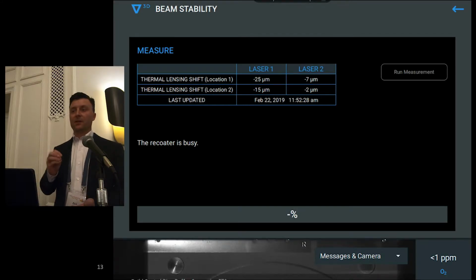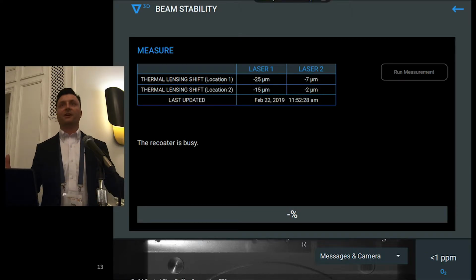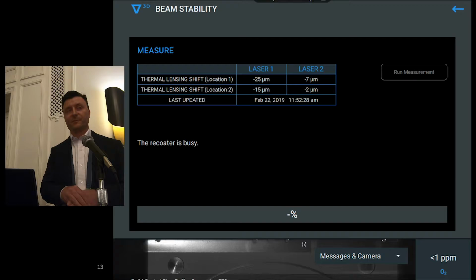Another big one, which Scott mentioned, was the thermal lensing. So how clean your optics are in essence. If your optics get dirty, the laser will hit the dirt often and will start to heat up the optics locally. You get an index of refraction change and your spot size changes. And when your spot size changes, the energy density delivered to the plate changes. And you can get some pretty nasty porosity effects if your spot size is not consistent.